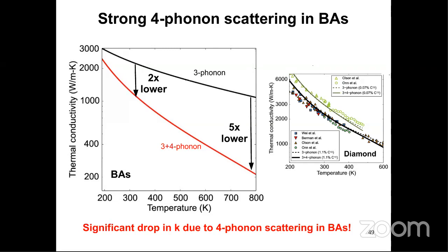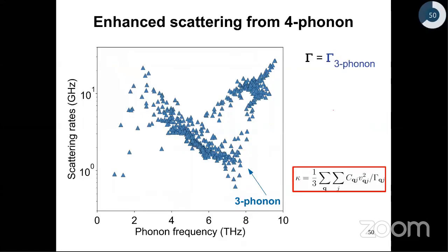Okay, so now we have an algorithm or a first principles code with which we can calculate the properties of phonons very accurately. So with this code, we can actually go beyond just calculating thermal conductivity, right? So we can actually look at the microscopic origin of such a large reduction in thermal conductivity of boron arsenide. So to do this, let's go back to look at how the scattering rates compare between 3 phonon and 4 phonon processes. So once again, to refresh your memory, I'm showing the 3 phonon scattering rates of boron arsenide that I had calculated and shown earlier.